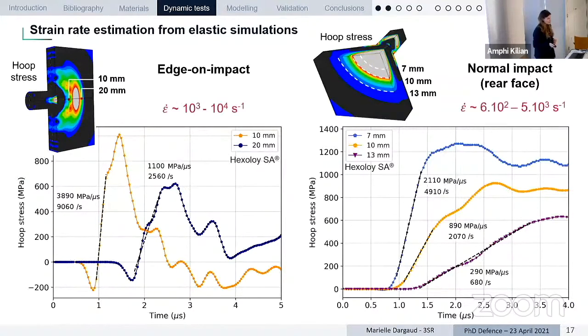From this, we can evaluate the level of strain rate reached at a given position in the ceramic, and we are between 10^2 and 10^4 per second for the two configurations, and we have an overlap, which is going to be interesting for comparison.